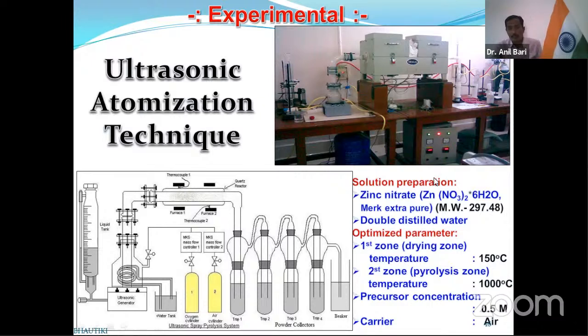This is the solution preparation and optimized parameters. That is the first zone. We maintain a temperature of 150 degrees centigrade. That is the drying zone temperature. And the second zone temperature is 1000 degrees centigrade. That is the pyrolysis zone temperature.